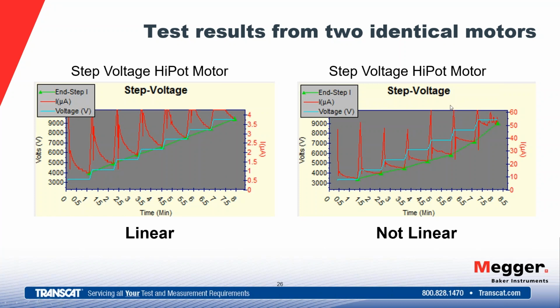Here on the left, we see that we do have a linear response all the way through the fourth point here. And we start getting slight nonlinearity and then a bigger jump here. And then at our final test voltage, we get an even bigger jump in current. So as we increase voltage, our current should respond in the same way. But on those latter steps, as we increased our voltage, our current increased more in the next step. This is an indication of insulation weakness.